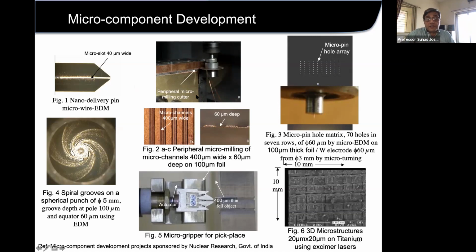These are micro exchanger plates. Not plates, but it's actually a 100 micrometer thick, 100 micrometer foil. And out of that, 40 micrometers we removed, and 60 micrometer we removed, and we kept 40 micrometer over there, so that these act as the coolant passages. So these grooves, though they look pretty dirty, are like 60 micrometer deep, and a small cutter was actually designed to make these grooves, a peripheral milling cutter.